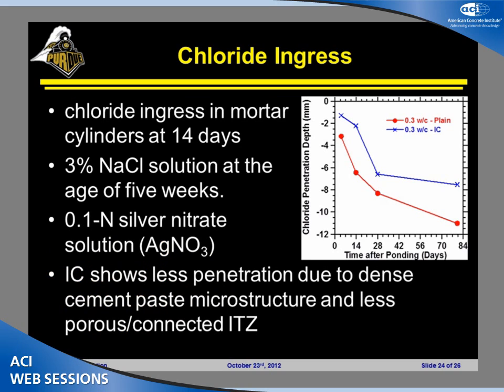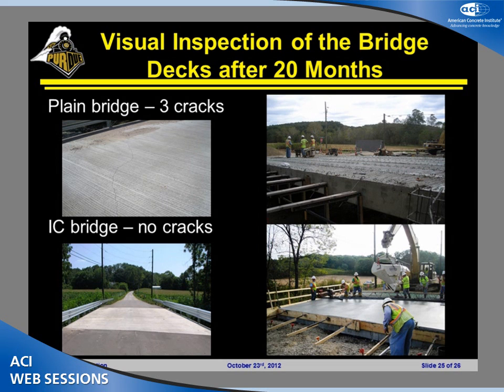Now, to tie this back into some of the field things that we had mentioned, we're really trying to understand the interrelation between restrained shrinkage, the stresses that develop in cracking, as well as corrosion. Here's a little bit of information on the chloride ingress, basically just looking at penetration depth. As I mentioned, this afternoon there will be several talks that get into all kinds of transport properties in a lot more detail. One of the things that we're seeing is that because of the increased hydration and the disconnection of the interfacial transition zone, we're getting less chloride transport in the systems that are internally cured. This, for this particular system, gives us a little bit of that information.